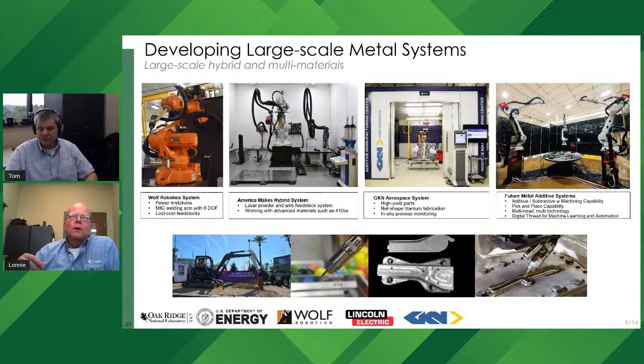So our big question was, well, get away from the wire, go to a pellet. So you're leveraging the injection molding industry. Get away from a liquefier, a heated tube, go to a screw, so you get your deposition rate up. That really transformed the polymer additive, where now we can make massive parts. We can put down 100 pounds, 200 pounds of material an hour. You can load with carbon fiber, glass fiber. You can do all kinds of things just by making that switch from wire to pellet.